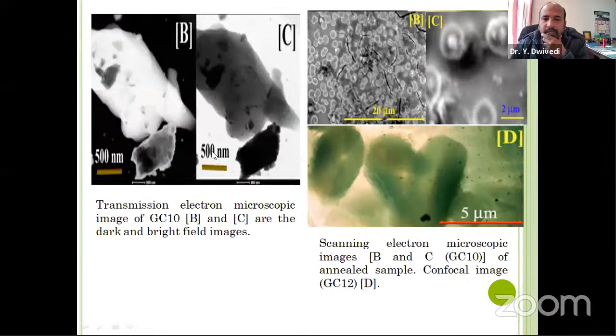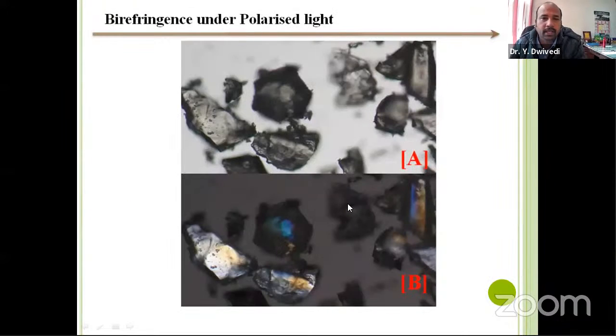So this is the transmission electron microscope image - you can see dark and bright field images, and the black spots represent the glass ceramic crystal formation here. This type of cone-shaped, two-headed cone type of structure, you can see while heating it for 10 hours. If you heat it for a longer time, you can see bigger crystals like this, and this is the confocal image for 12-hour heating.